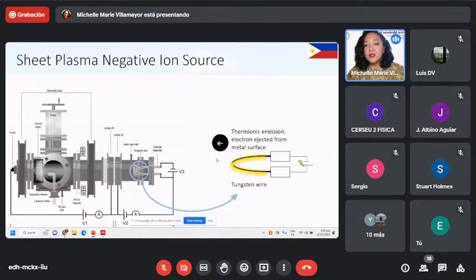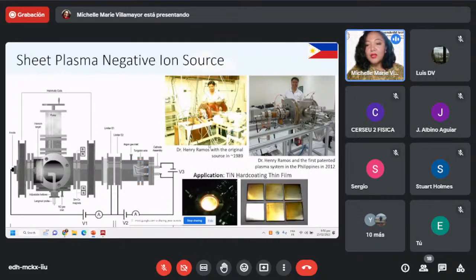These electrons are then used to ignite the argon gas, which becomes argon plasma. And then the argon plasma is guided towards the extraction chamber. It sputters out the titanium target, and the titanium material reacts with the nitrogen, which was also fed in the extraction chamber. With this, we are able to deposit titanium nitride hard coating thin films.